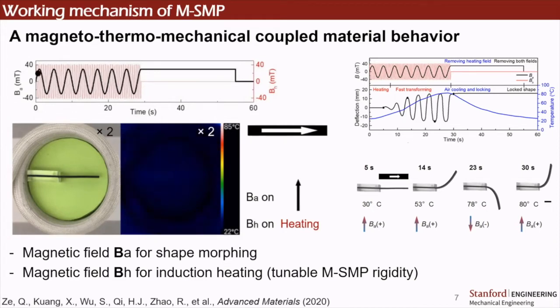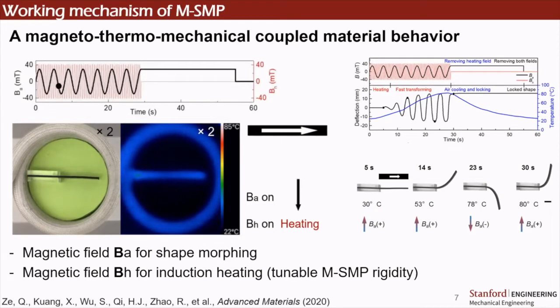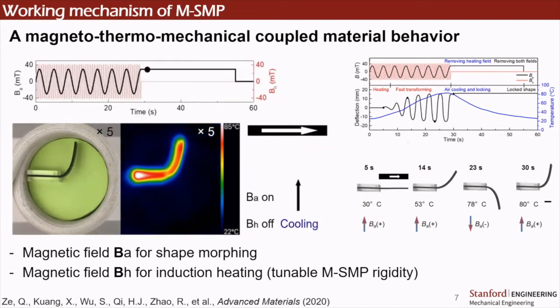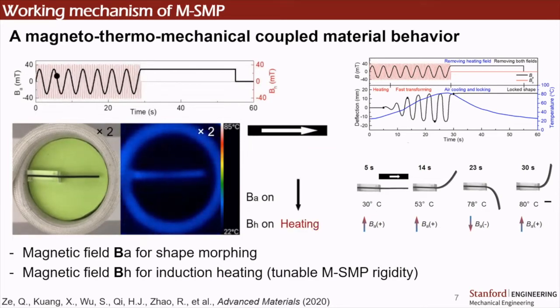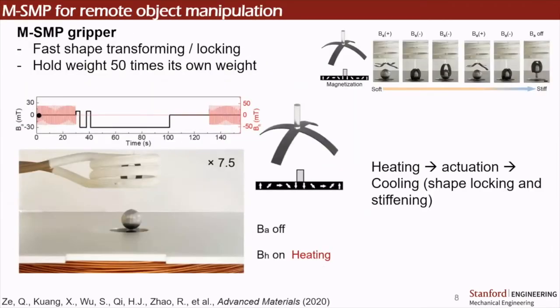If we look at this video here, through the thermal camera we can see the material gradually unlock because of the temperature increase. Now it becomes really soft. It can very easily deform and have very large shape change. After that, we can cool it down so that it locks its deformed configuration. At this state, we don't even need to apply any external magnetic field, and it will always stay locked in the deformed configuration. Based on this material, as I mentioned, soft materials are great: they can be deformable, and it's very easy to generate different morphing shapes.